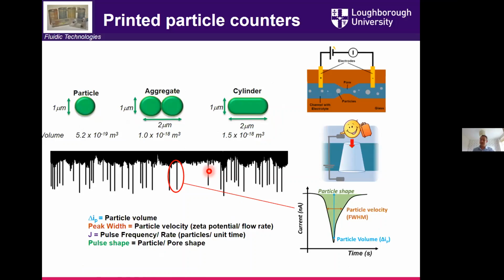The other one was electrochemical processes. And so we wanted to put electrodes into these flow channels where we would flow the droplets through, and the electrodes would tell us something about it. As a test case to embedding electrodes into this, we went back to looking at resistive pulse sensing or Coulter counters, where you embed two electrodes and you apply a potential between them. That induces a current flow between these two electrodes. And every time a particle or droplet sits inside that narrow channel between them, you see a decrease in the current, and you can tell something about those particles.